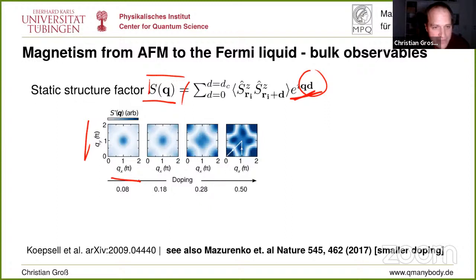And then you see basically with increasing doping, so you see here the doping levels is pretty heavy doping. So this is 0.5 doping, like half of the atoms in the system. We see basically that peak smears out. And then we see something very interesting happening. We see new peaks appearing. So we see peaks appearing at wave vectors that are incommensurate with the lattice. So we're seeing really incommensurate magnetic correlations appearing here.